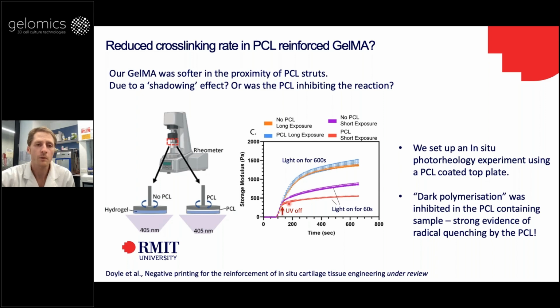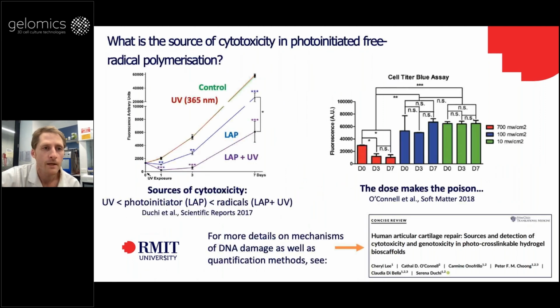And in our normal case, we actually only use a 60-second light exposure. So if that's the case, this supports the idea that the PCL is actually quenching some of those radicals and stopping that reaction faster than it would otherwise. And that's why we were seeing softer material only in the vicinity of the PCL material. So, another example of how this technique can give you new insight.